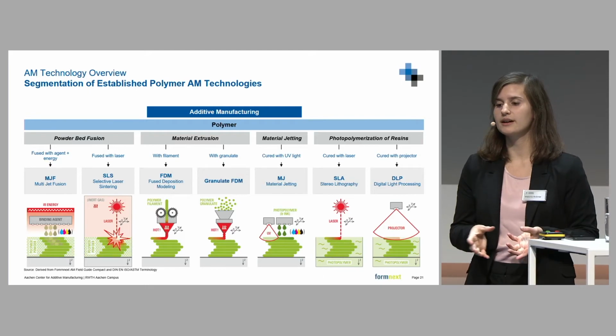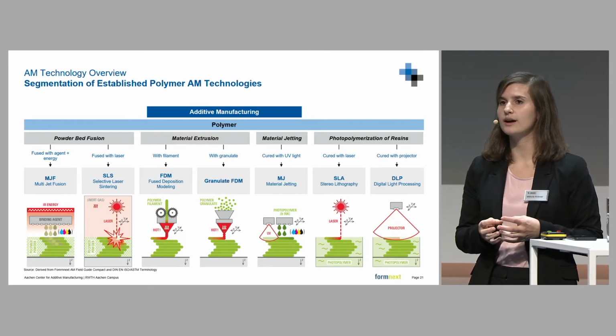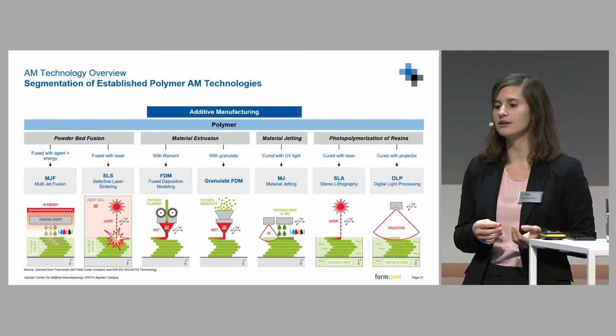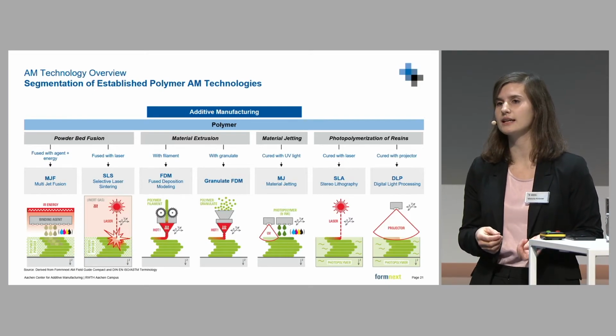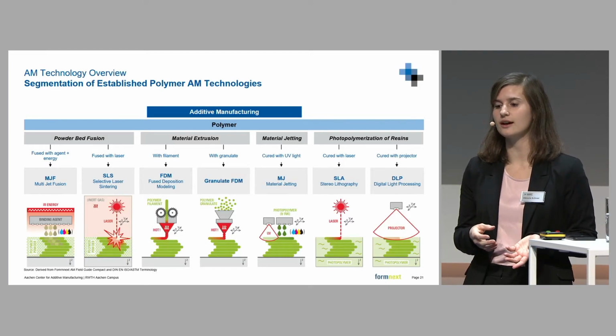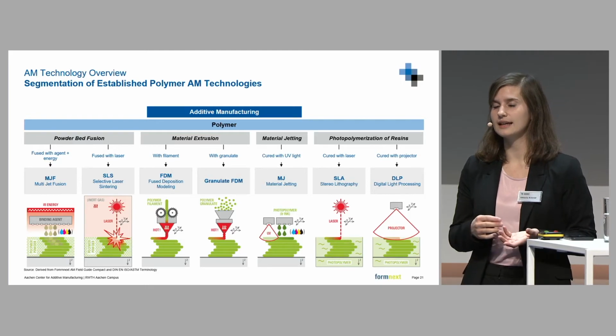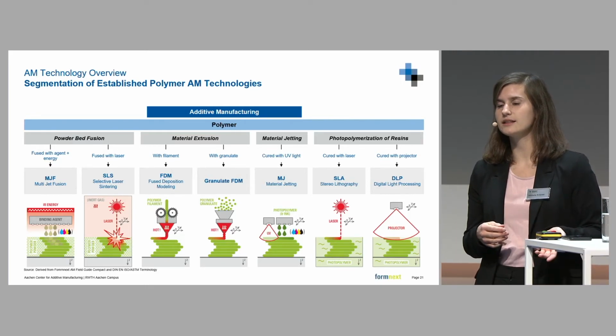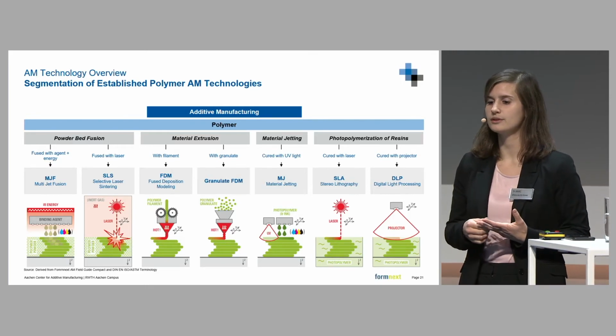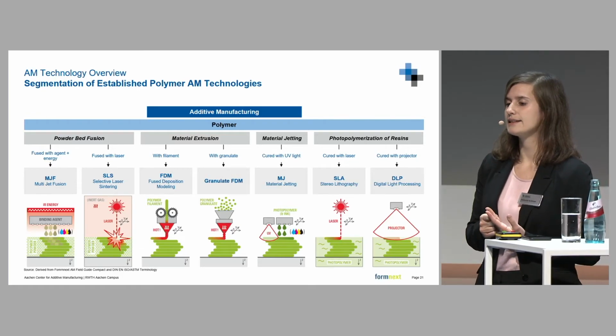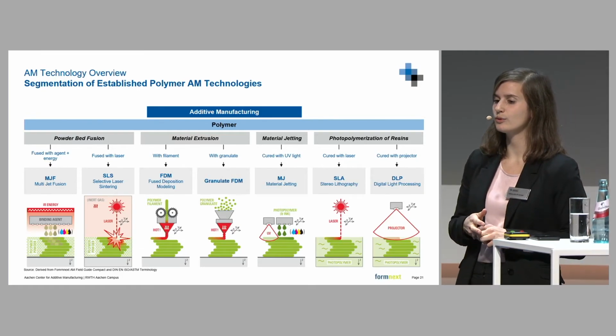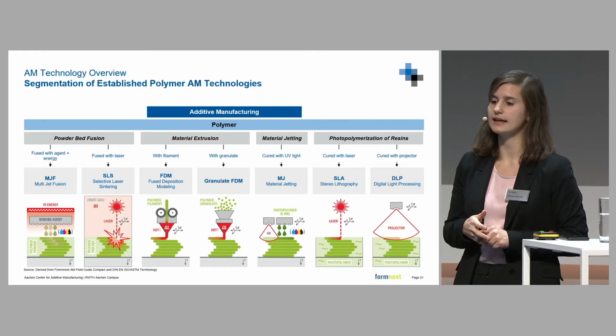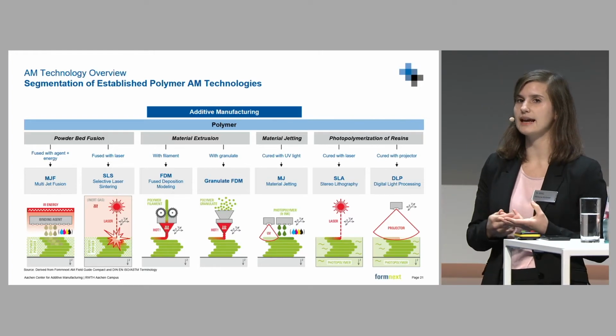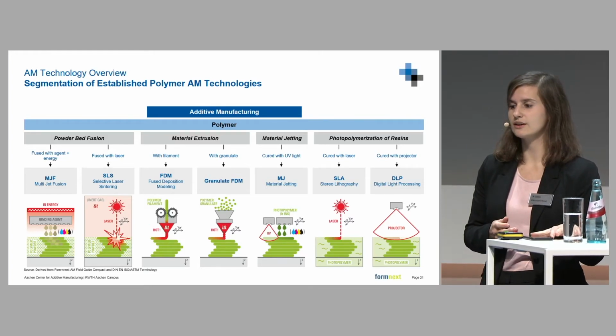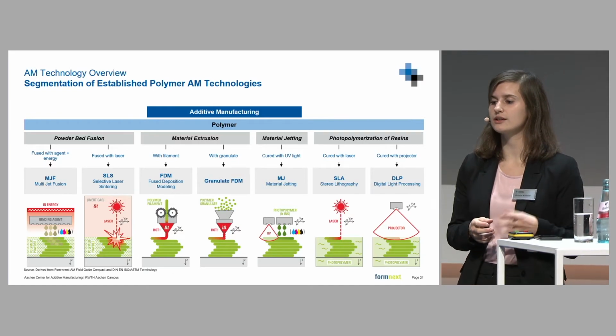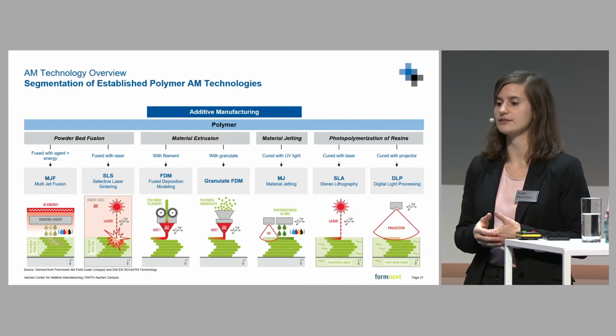And then in the middle part, we have material extrusion, where we have a filament or a granulate that's being melted and deposited and solidifies when it cools down. So we stack the building layer by layer, either through filament or pellets. And then we have material jetting, where material is cured with UV light. And on the right-hand side, we have processing of resins, either cured with a laser or cured with a projector.